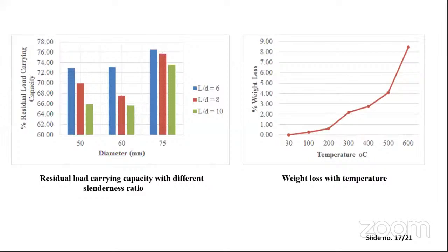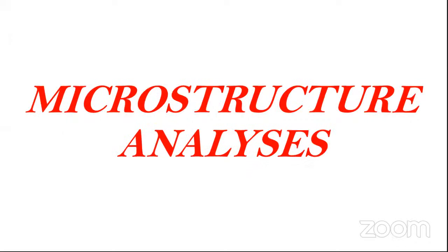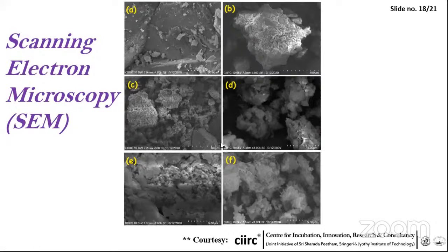Here we can see the percentage decreasing with increasing slenderness ratio, and also the percentage of weight loss. We can see here that the concrete is inside the steel tube. Even then it is losing its weight by 8 to 9%, tested up to a maximum of 600 degrees centigrade. So this is the microstructure analysis. In it, we can observe the morphology of these images. Some pores are coming in figure D, and we can observe some unblended cement particles. Because of these, the concrete sample consists of irregular particles with micro pores, and this may be the reason for poor performance in strength and durability. So this is one reason I found from the SEM.